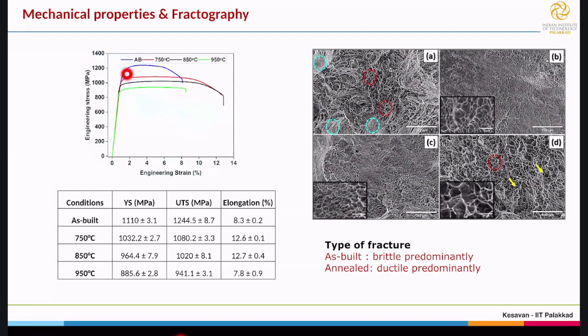It is showing very high strength. The strength is almost 1,200 MPa, which is extremely high strength, and which is good. But you see the ductility is very low, right? So here the ductility is about 8%, very little ductility, which is not good for biomedical applications.